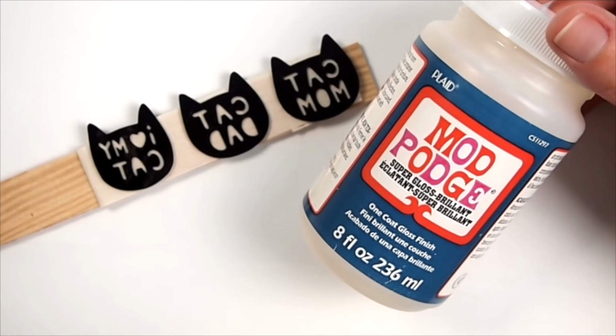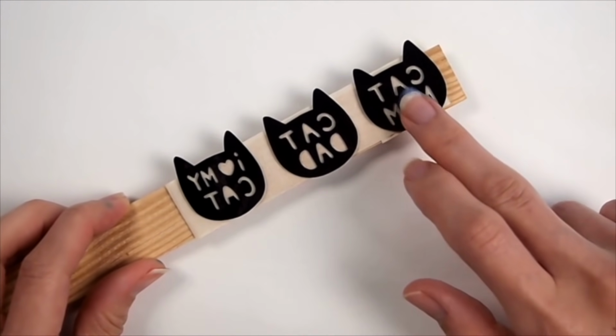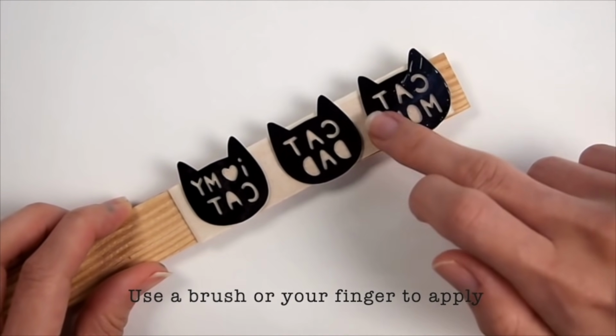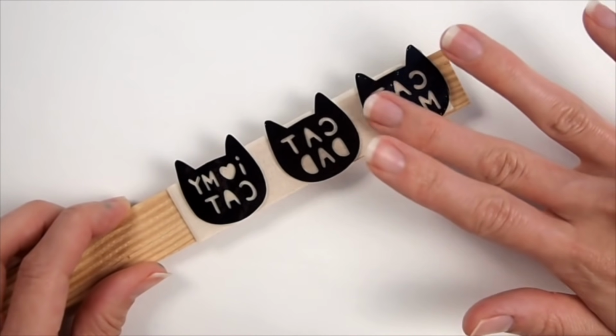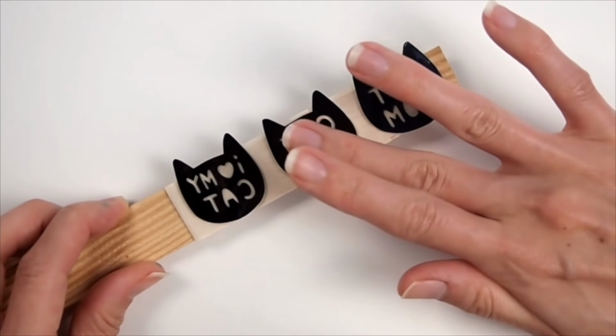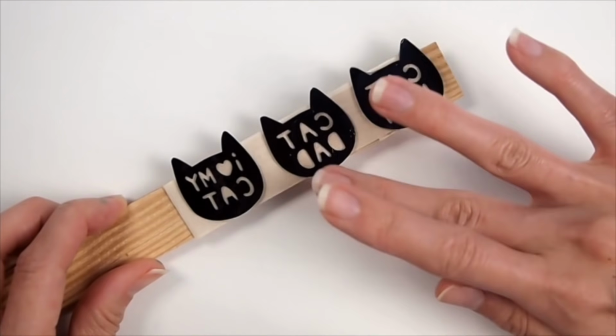Now if you use permanent markers, make sure to seal the ink with a decoupage medium such as Mod Podge before the sealer to prevent any of the ink from bleeding or smearing. If your sealer is water-based, then don't worry about it. If you are using resin, both UV or two-part, seal the plastic with a decoupage medium before the resin layer. Why? Because resin doesn't bond too well to polystyrene. The decoupage helps with that, and it will prevent the resin from peeling off of the plastic.